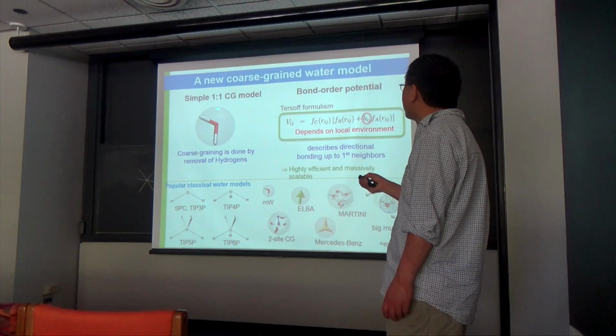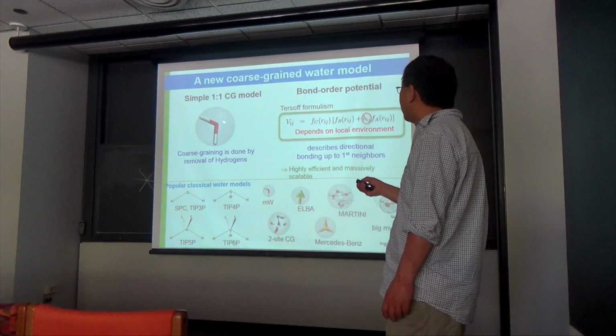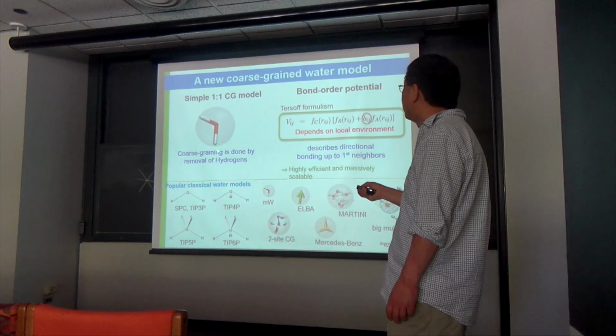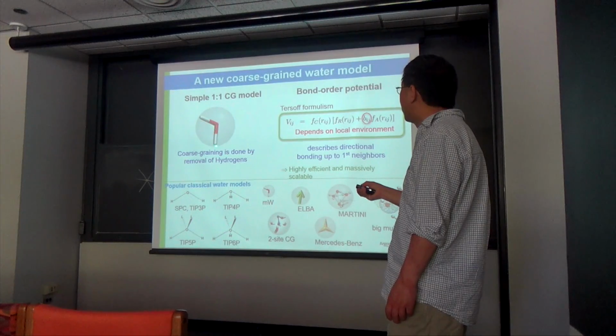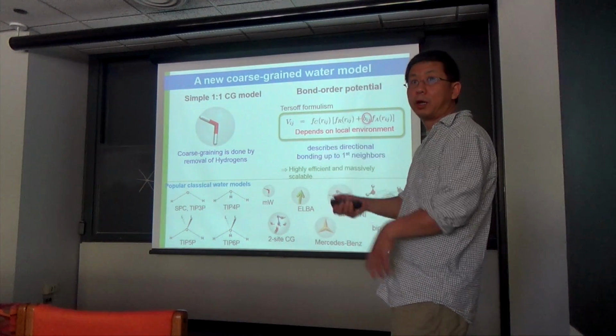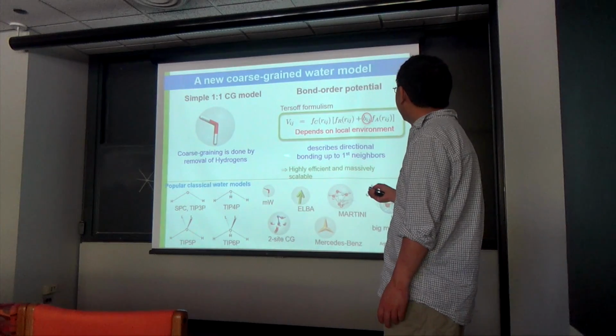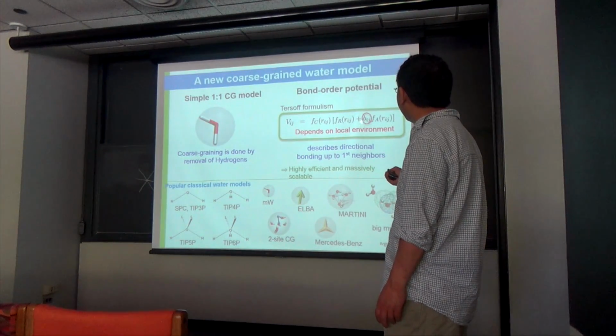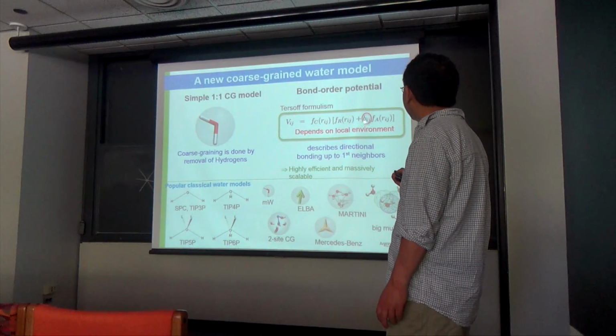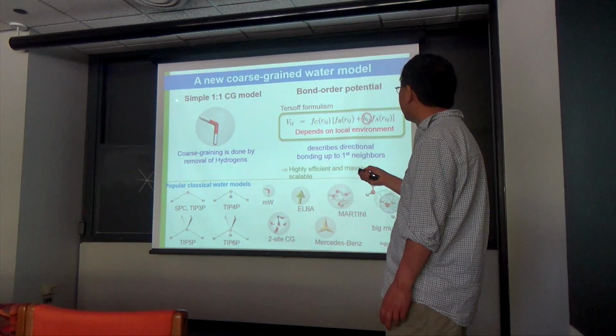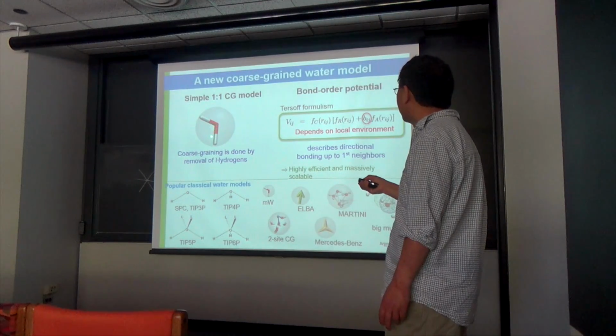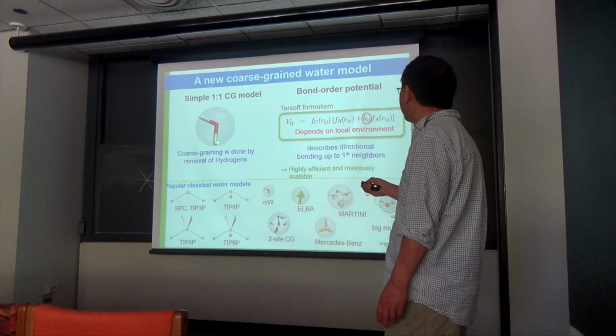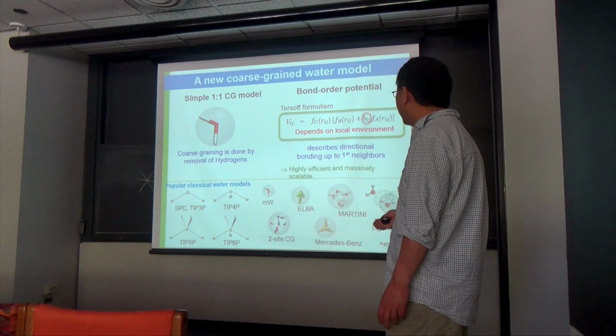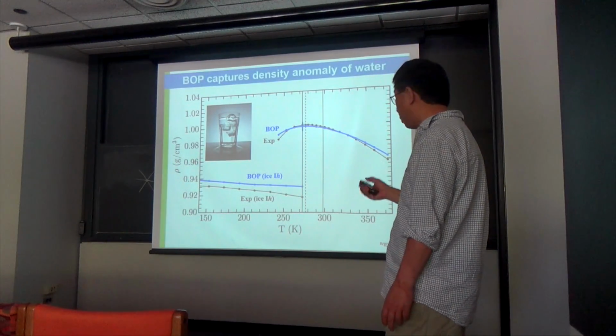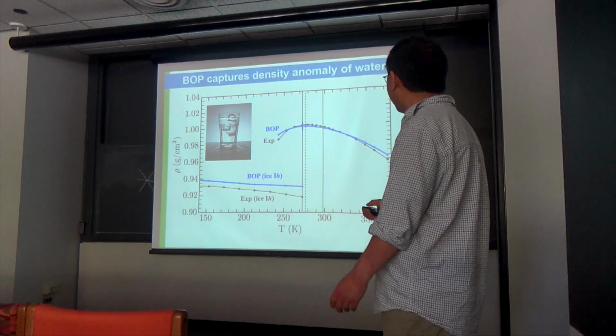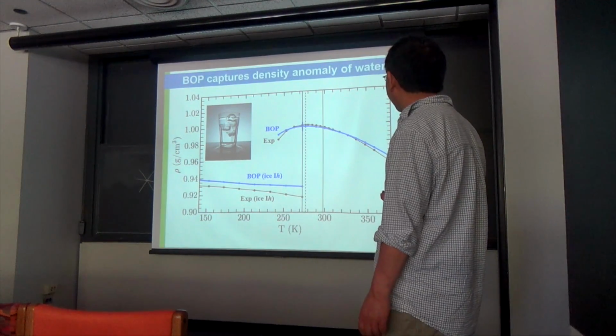And for the water model, which I showed you before, the typical water model does not really take into account hydrogen bonding, and especially the relative angular distribution of hydrogen bonding in these water models. So what they're doing is adding another term in this force field to take into account the anisotropic interactions in the potential distributions of this force field. And so they can calculate water compared with the traditional models they have in coarse-grained molecular dynamics simulation.